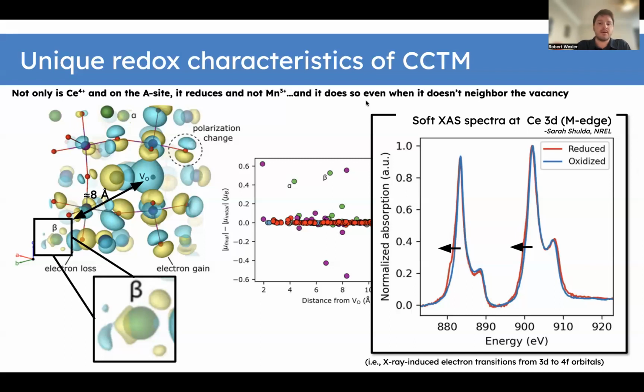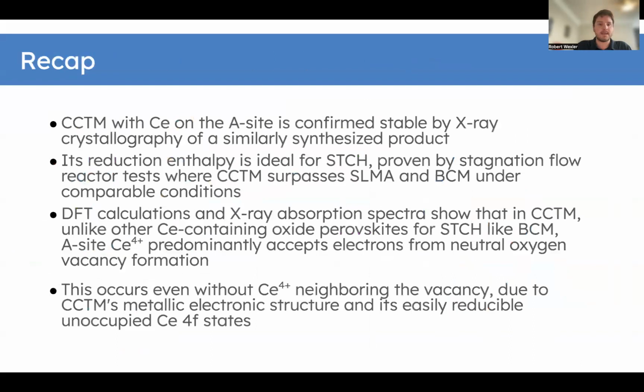So this constitutes a really, really exciting example of where theory was able to design a material with, of course, experimental input and guidance, but kind of a synergistic workflow to model ourselves on in the future. So to recap, we discovered CCTM with cerium on the A site, which was very interesting, and a stable crystal structure analyzed by X-ray crystallography that matched our predicted structure. Its reduction enthalpy is predicted from DFT to be ideal for STCH, and this was proven by stagnation flow reactor measurements, where CCTM actually surpasses SLMA and BCM under the same conditions, and just slightly surpasses ceria under lower temperature conditions compared to ceria's optimal conditions.